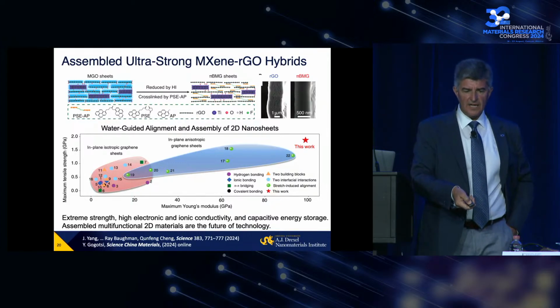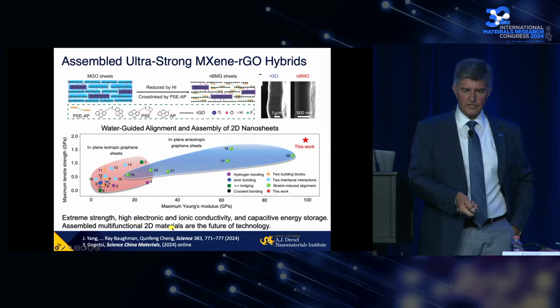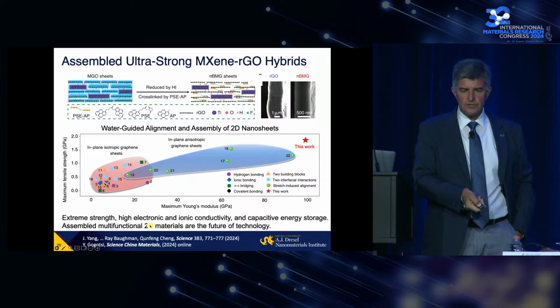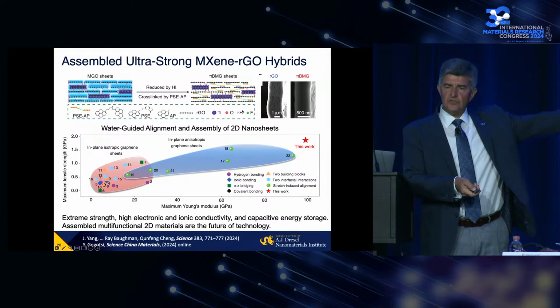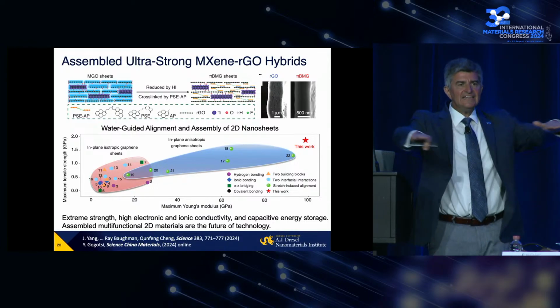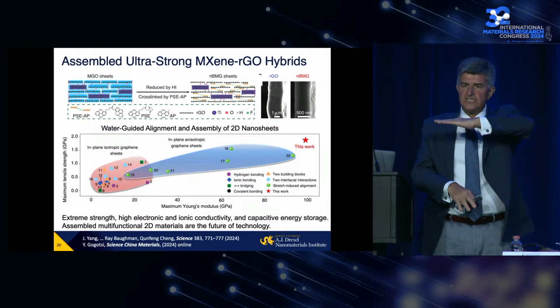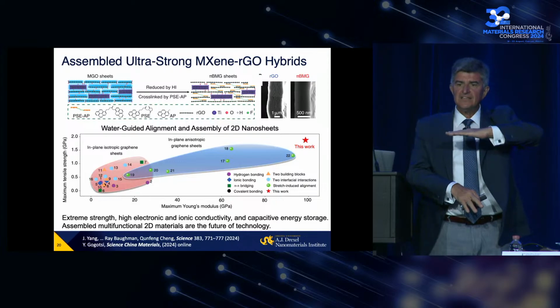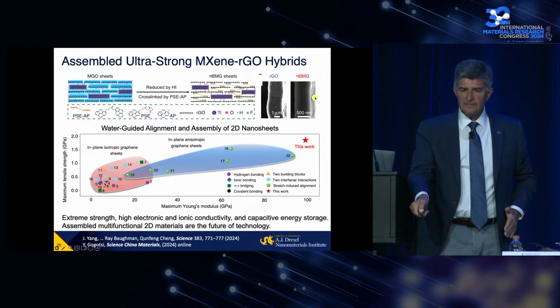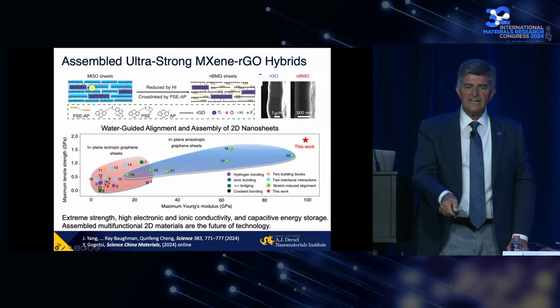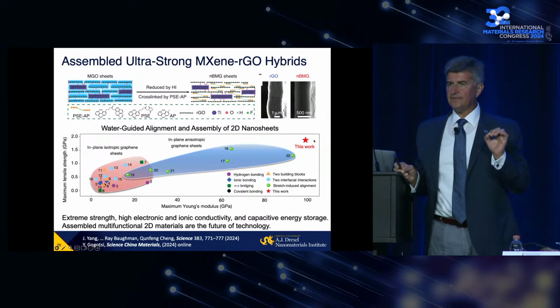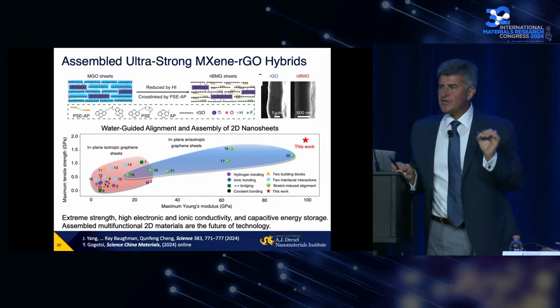This is a paper from the work of Qunfeng Cheng from China and Ray Baughman, published in Science. Qunfeng published a series of 3 very interesting papers in Science. They report combining MXene with graphene, using graphene oxide water layers to align and stretch with much more rigidity than graphene alone. MXene is not flimsy unlike graphene layers, making a straight, well-aligned film and binding with organic molecules. They get a mechanical strength of 1.8 gigapascal, which is twice the strength of steel.